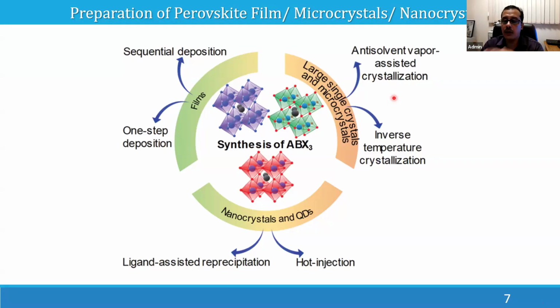You heat the material to like 100 degrees Celsius or 120 degrees Celsius, then you cool down slowly. Once it reaches a lower temperature, normally these materials will start crystallizing. Similarly, you can make nanocrystals or even quantum dots. Nanocrystals have a size below 100 nanometers. Quantum dots are normally below 10 nanometers. These microcrystals and single crystals are normally in the micron to milli to centimeter scale. Even 1 or 2 centimeter size crystals can be made.